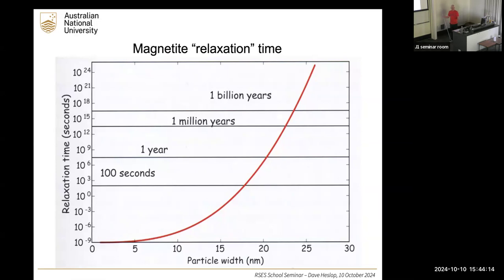The problem is, of course, we're working at ambient temperatures. So even though it's recorded the Earth's magnetic field, there's this thermal activation of the magnetic lattice within the crystal that slowly works to randomize that magnetic signal. The amount of time it takes to randomize is what we refer to as the relaxation time. So you can see this is for magnetite particles. If I take a magnetite particle with a width of around 17 or 18 nanometers, that paleomagnetic signal would actually be randomized in 100 seconds. Obviously, not a lot of use for paleomagnetism.